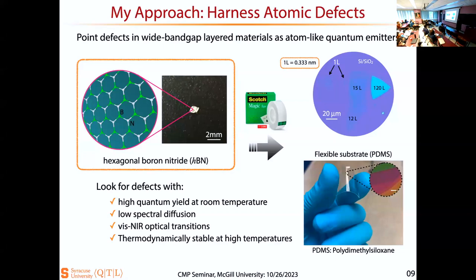In these crystals, we use flux tape and transfer them onto a silicon substrate. These are some of the flakes which I have. One layer is 0.33 nanometer, so based on the thickness measured by AFM, we can extract how many layers it has. It can go from literally one layer, to 15 layers, to 120 layers. These are only some of them, and there are many different colors.